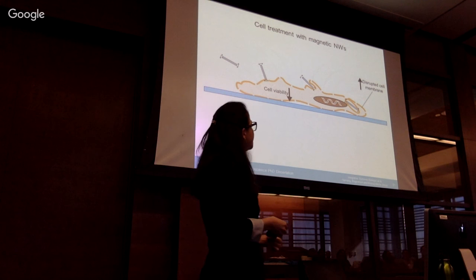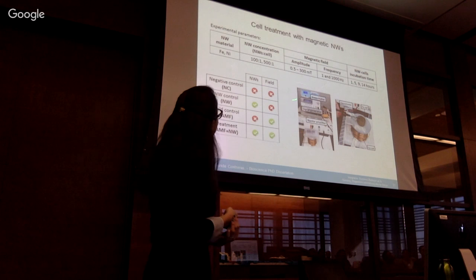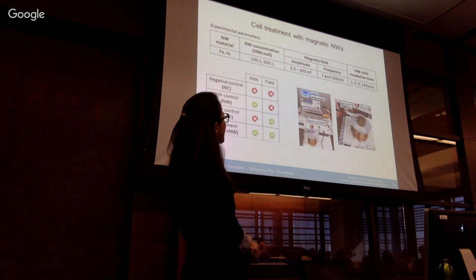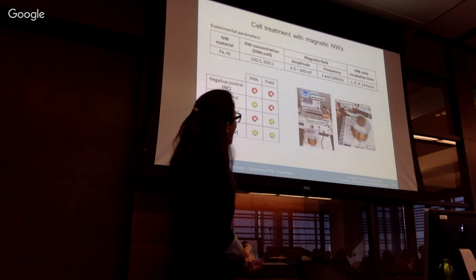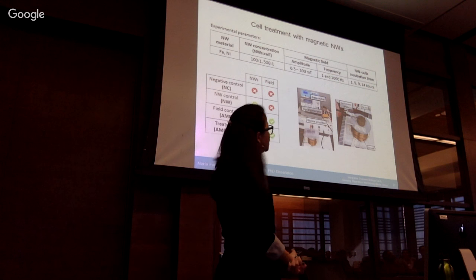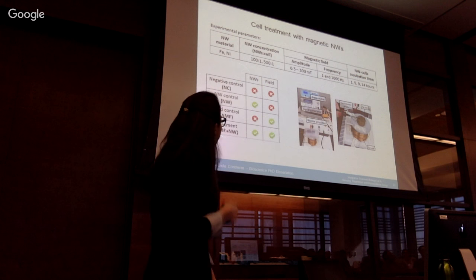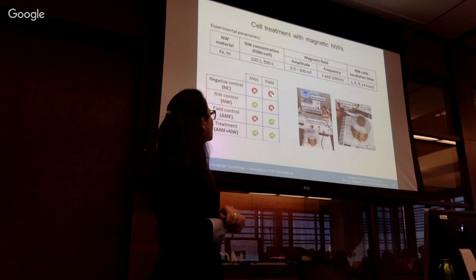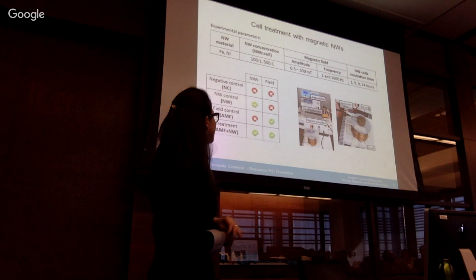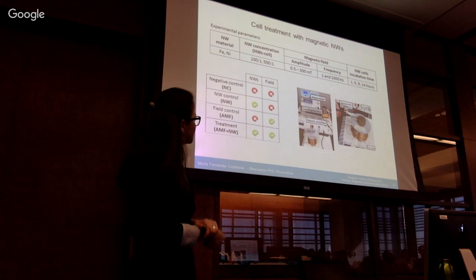Okay, these are the different conditions I used for the treatment. The nanowire material, iron and nickel, the concentration 100 and 500. Field amplitudes range from 0.5 up to 300 millitesla, and the frequencies used were 1 and 1,000 hertz. The incubation times of the cells with the wires were 1, 5, 9 and 14 hours. For each set of experiments, I have three controls and the actual treatment. So I have my negative control where no wires or field were applied, a wire control where I only added nanowires, a field control where I only applied field, and the treatment that consisted of the combination of the two conditions. And this is the experimental setup I used for that.